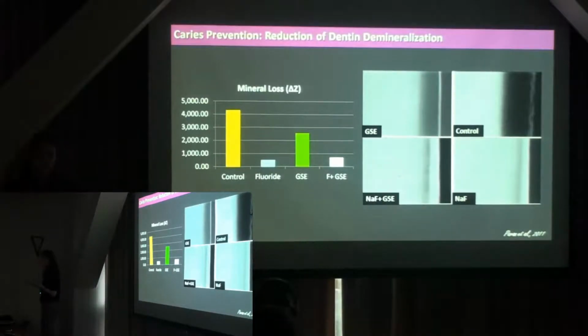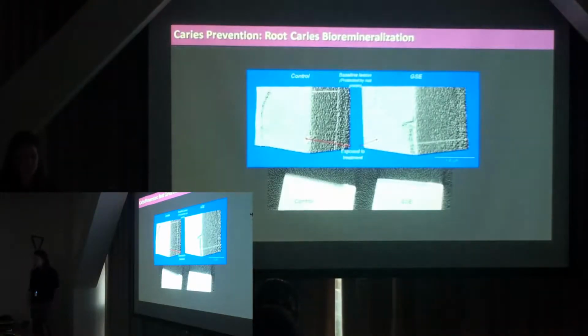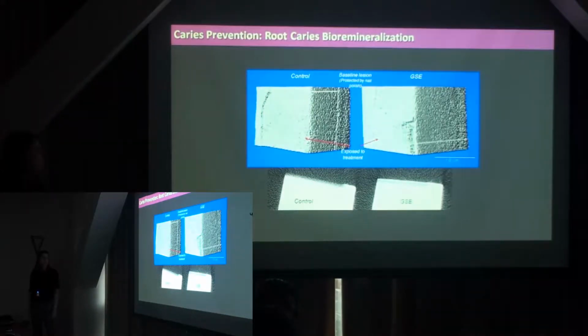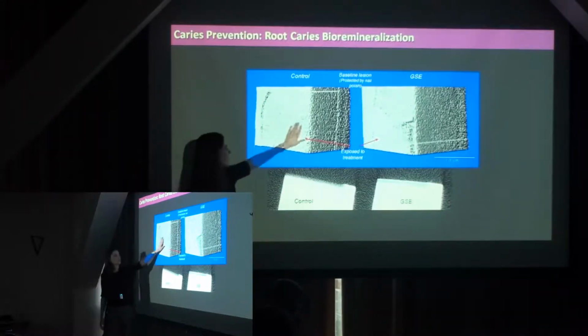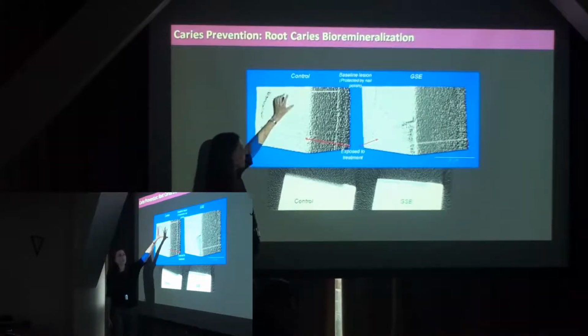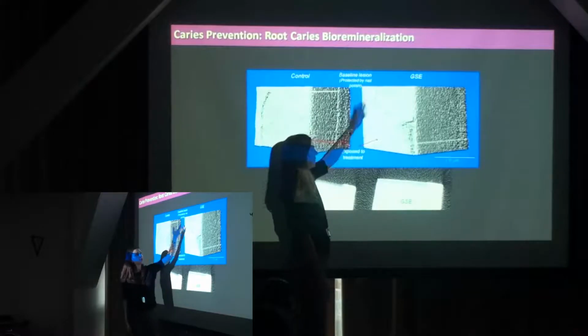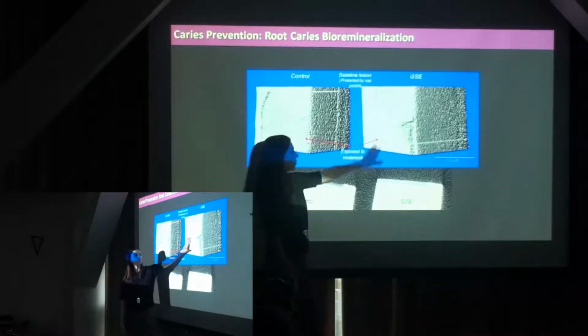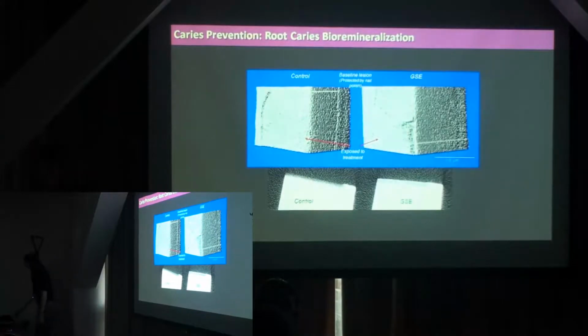So we look at the mineral loss by using microradiography, and we can quantify this mineral loss. We even did some studies where we introduced collagenase, since you would expect some of that degradation to take place in the mouth, and we've seen very promising results with this. So this is what we've been cooking in the lab, and hopefully we'll send a proposal in. And then we can use fancy tools like CT scans to look at the remineralization. On the surface that lost mineral, part of it we coat with nail polish so we have a reference point. Then we try to remineralize, and this is the start of the remineralization process over the surface.